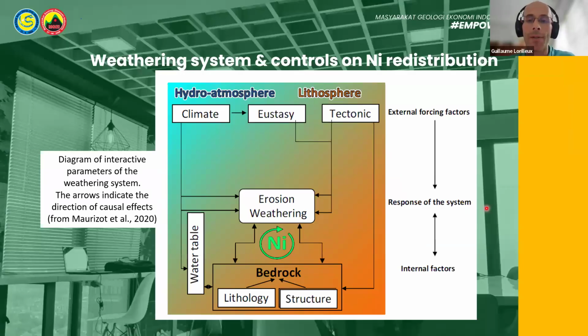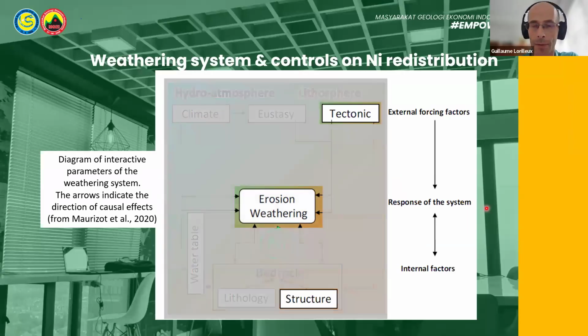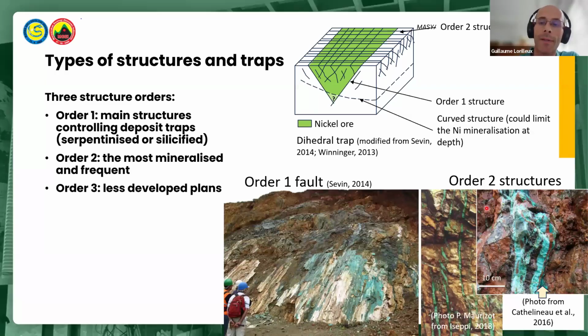We now focus on the influence of structural controls in relation with tectonic activity. So it's closely related to the previous part, but going into more detail on the actual structural controls. The inherited serpentine-rich fracture network controls water infiltration, and therefore the incision of the weathering surface and the deepening of the weathering profile. The plateau deposits are generally controlled by the intersection of two or more orders of structures, resulting in complex patterns such as horst and graben structures, high-angle cross-cutting furrows, and ridged or egg box structures. This is an example here of a dihedral trap formed by these conjugate structures.